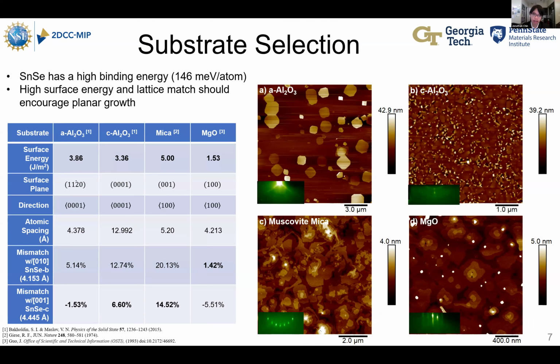Yeah, okay. One thing that we're thinking that may be helping with the surface energy, and something I'm still trying to work with theorists to simulate, is that perhaps the cleaving and annealing preparation steps for MgO are increasing the surface energy higher than those same effects are on the other substrates. So this is the surface energy of MgO as prepared. It may be different when it's in our vacuum chamber. But that's something we're still trying to determine the exact dynamics of.